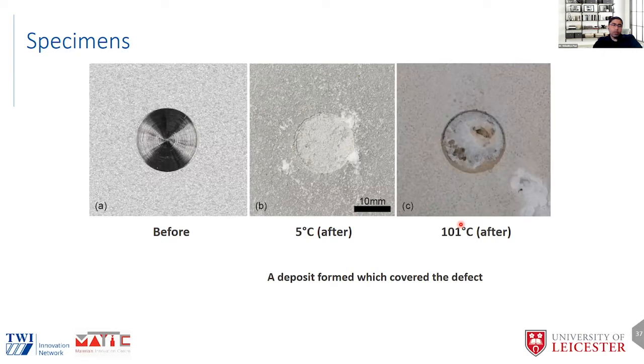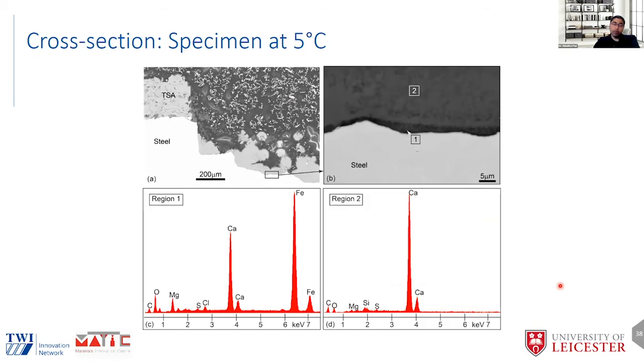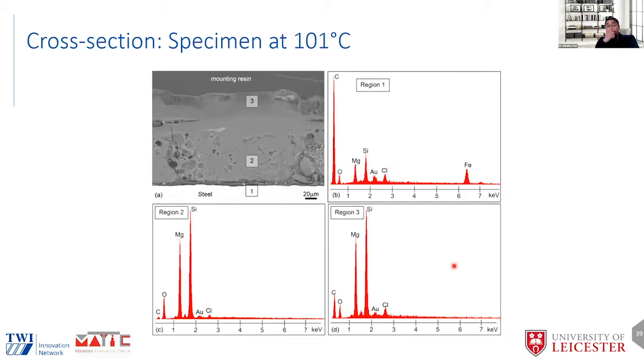When we looked at the samples, again, you can see on your left, before, it's a nice and shiny steel surface, and after, we get some white deposit. We cross-sectioned these samples, and at 5 degrees, we found a very, very thin layer of magnesium hydroxide close to the steel surface, and a lot of calcium carbonate above it. And in boiling seawater at 101 degrees Celsius, most of the sample is covered with magnesium hydroxide. There is no calcium carbonate.